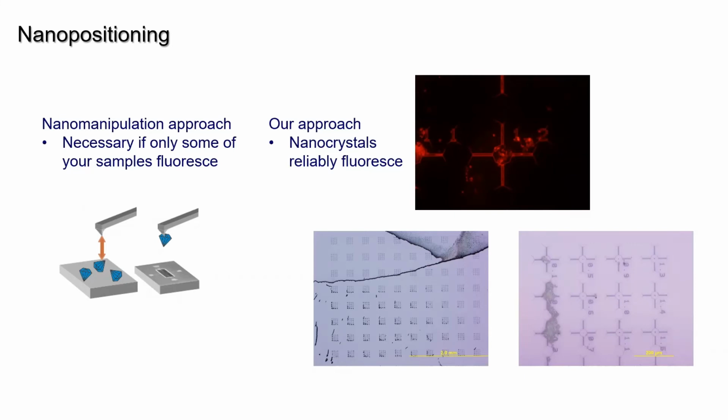But what we found, because you can make these things in solution, like I mentioned, you just take nanocrystals in water and you just drop-cast them onto a bunch of holes. That's what these are, either bullseyes or the hole in the middle. What happens is that they tend to clump around the holes, just naturally. Why is that? We don't know, first of all, but you can imagine if you have a hole, there's water in it.